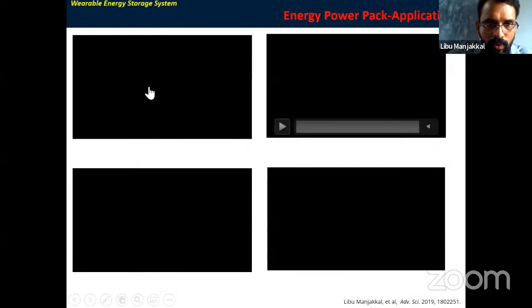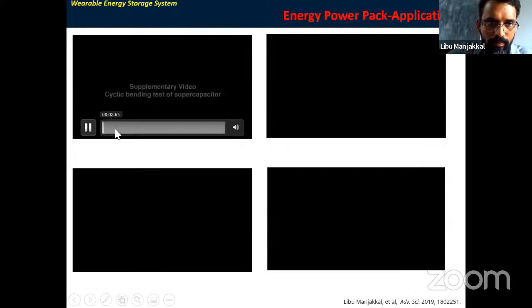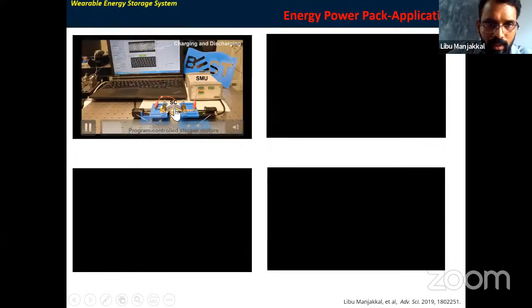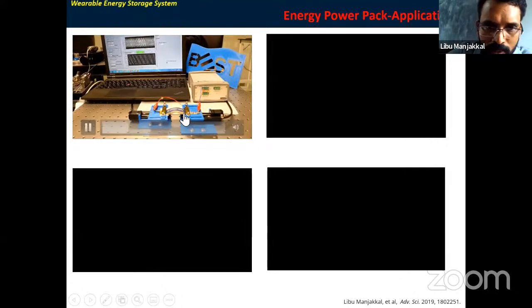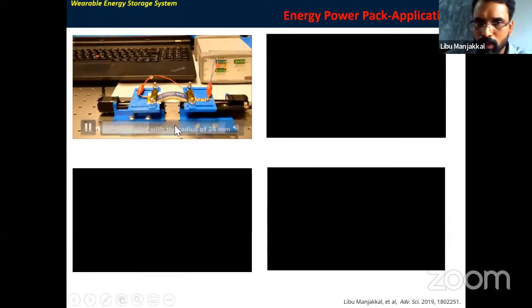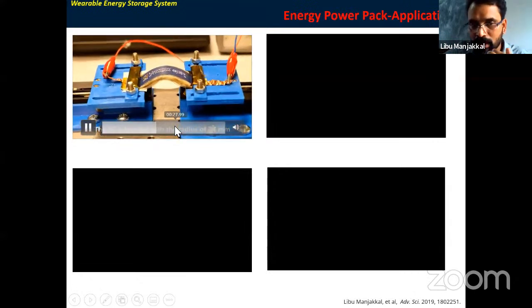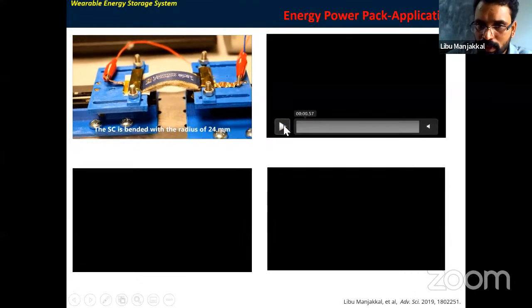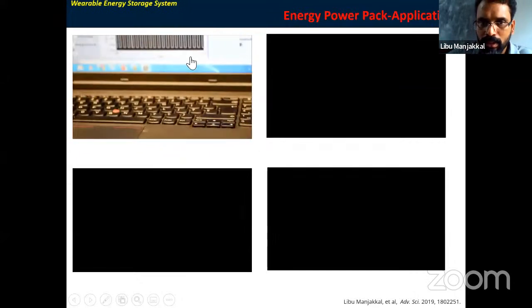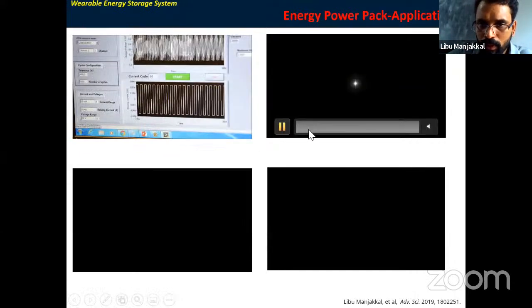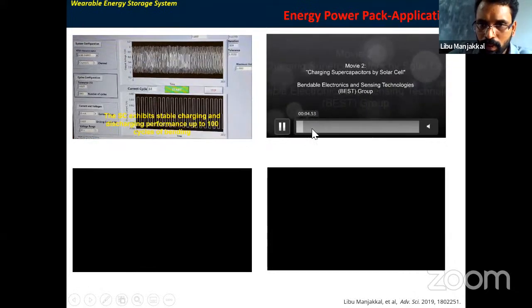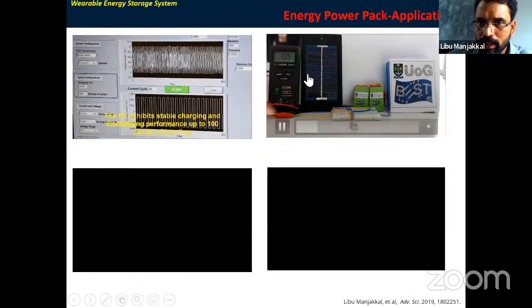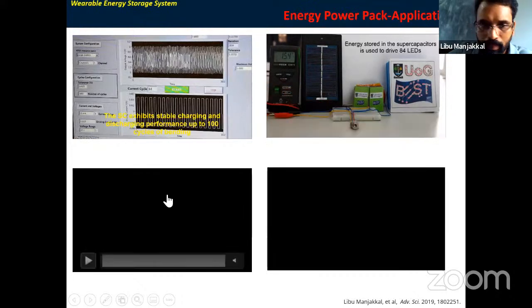Maybe I can show you some videos in this aspect. Here you can see the flexibility of the device. Here the supercapacitor is attached to a 3D printed cube, and you can see that it is bending almost 24 mm. I did almost 100 cycles here, and again I continued this with more than 1000 cycles of cyclic bending, and it shows a stable performance. And also here you can see a solar cell charge the supercapacitor and then power the LED.